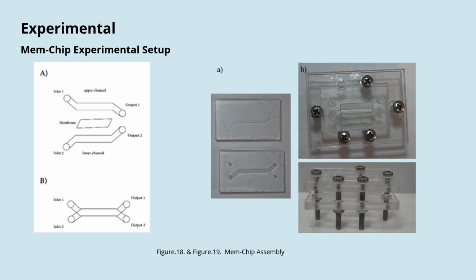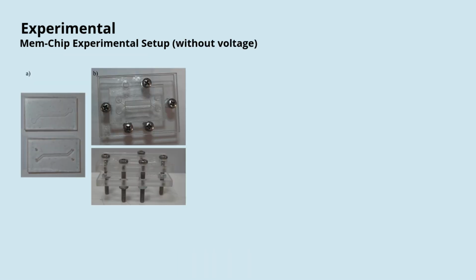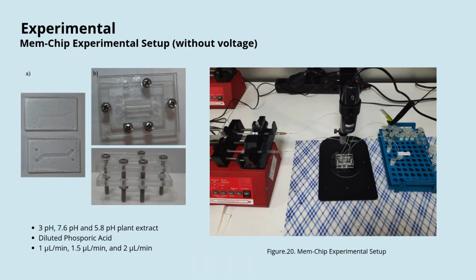The assembled chip is compressed between two PMMA plates using bolts and nuts, providing mechanical strength and leak resistance. The MEM chip was operated without voltage and used plant extract solutions at three different pH levels: 3, 5.8, and 7.6. And they have used different flow rates: 1, 1.5, and 2 microliters per minute.